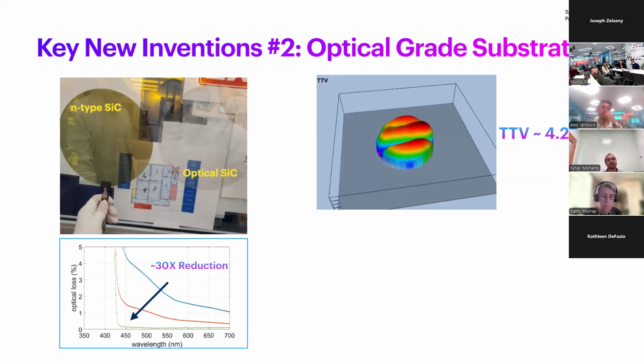The second key vector for improvement in enabling optical grade silicon carbide was the flatness improvement, the TTV improvement. Once again, due to the long travel distance of the rays inside the waveguide, the flatness, as defined by the TTV, is critical to maintain the high resolution of the display. When we started the project, the TTV of the silicon carbide substrates was over 4 microns, which might seem pretty low for the semiconductor industry, which is the primary user of silicon carbide, but produces unacceptable display artifacts when used as display waveguides. This was especially a hard challenge, considering the hardness of silicon carbide, as defined by the Mohs hardness, is just below diamond, which is the hardest material on the earth.